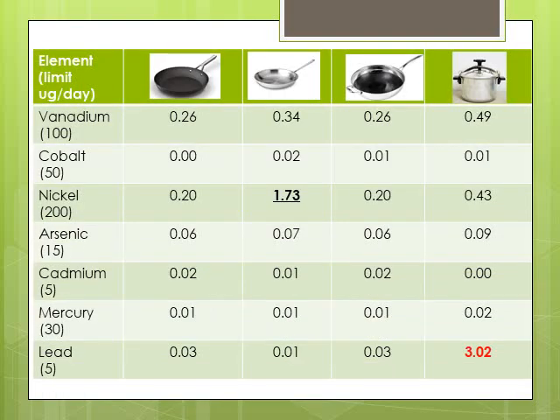So these are the summary, and I have everything here. The major concern was this old, bizarre aluminum pressure cooker that had significantly higher lead than anything else. And also the stainless steel 18/10 that had nickel, but the limit is 200, and we see only near 2, like 100 times less.